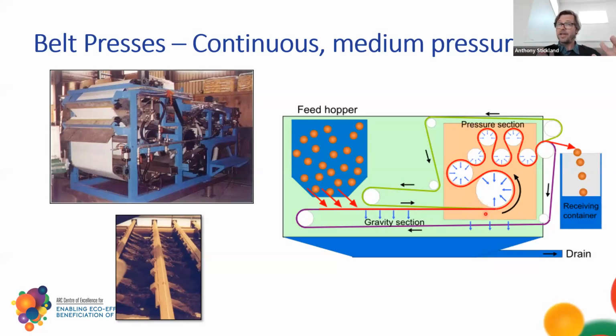Belt presses have a little bit of this shear effect because the belts have the thickness of the cake. One has a larger radius than the other, and so as they're going around each roller, they're actually moving relative to each other, or there's a force acting on that, which provides an enhancement. If we did the calculations and showed that if you were just relying purely on compressional dewatering, there was never enough time as it went around those rollers to actually achieve what you see in industry.